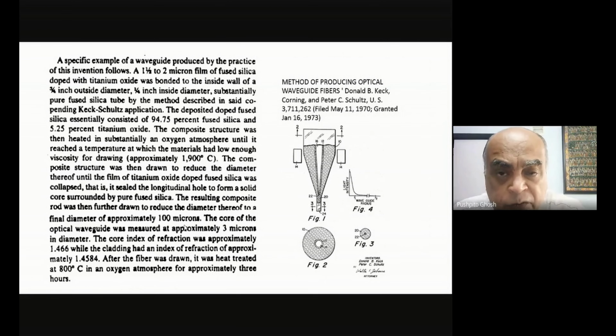So you can actually work out for yourself that even if I take a tiny glass piece, maybe a foot long, I can pull on it and make these fibers, and I can generate kilometers of fiber from that. The core of the optical waveguide was measured at approximately 3 microns in diameter. So they are talking about a cladding to core ratio, roughly not 100:1, but closer to 35:1.